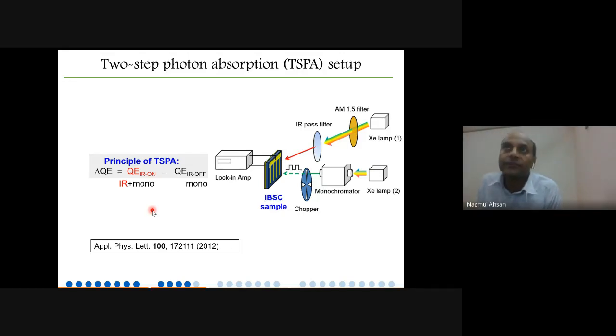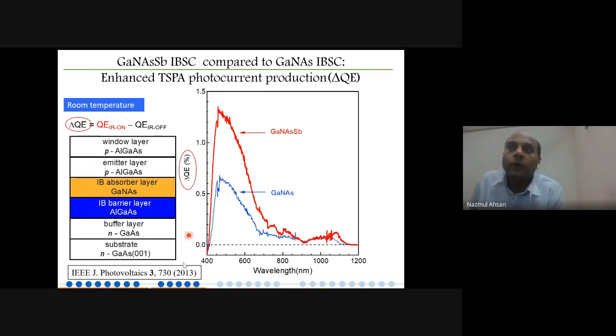Okay, and this is another paper in 2013 in which we demonstrate the 2 photon absorption due to the intermediate band. Here the wavelength is the wavelength coming from the sunlight, and the vertical axis, delta QE, tells the amount of long wavelength photons you can convert to electrical current. So you see the dotted line: we confirm that if you don't have an intermediate band, you cannot convert by 2 photon absorption and you don't get any electric current. But if you have an intermediate band in this kind of solar cell, then you can generate current due to 2 photon absorption.